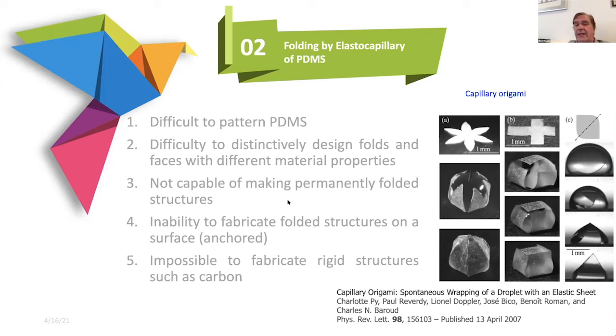Number three, you're not able to make permanently folded structures. Indeed, when the droplet is gone, the structure falls back apart. It's also not possible to fabricate folded structures on a surface. Say you want to have this flower anchored or this cube anchored with this face. With PDMS, that's not easily done. Number five, it's impossible to fabricate rigid structures such as carbon. And so these five items were driving us to look at alternatives to make